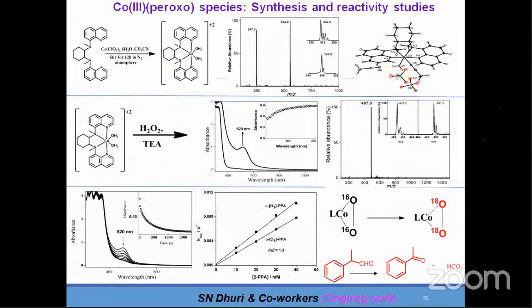Similar to that, we also prepared a tetradentate ligand, and this time a cobalt compound, and we thought we would try some peroxide intermediate. You can see this is a tetradentate ligand, with a trans-cyclohexane and then a quinoline-based moiety. So we prepared a cobalt compound. We characterized this compound by ESI mass. We have a crystal structure also of the starting compound, and then we again tried to trace intermediates. We could get a peroxide intermediate, not other intermediates.